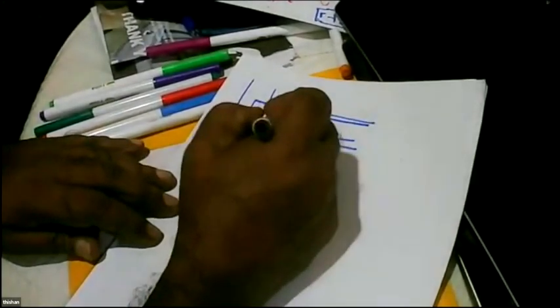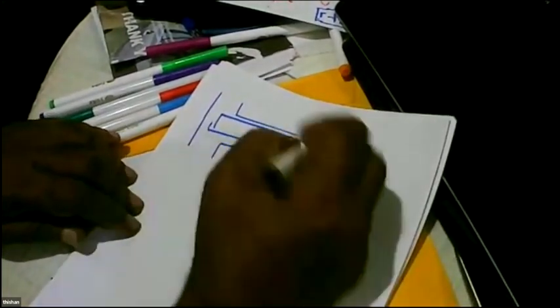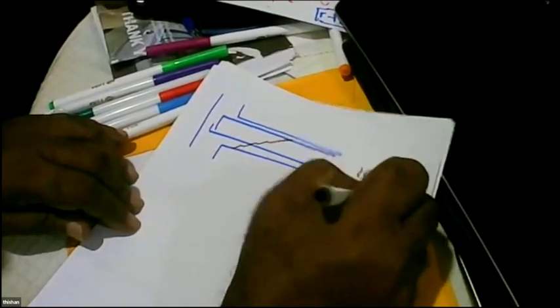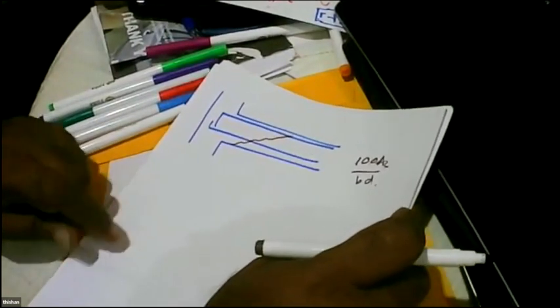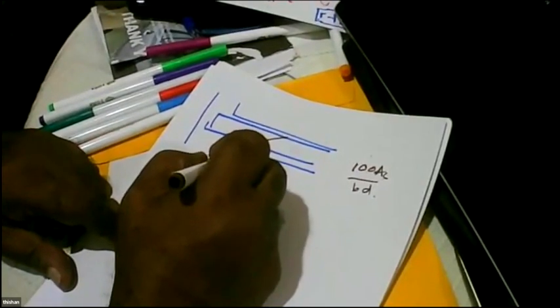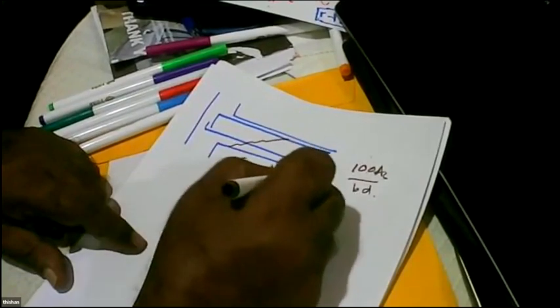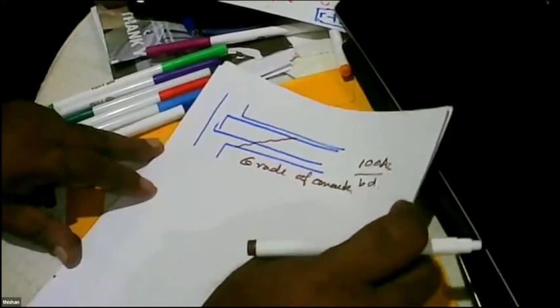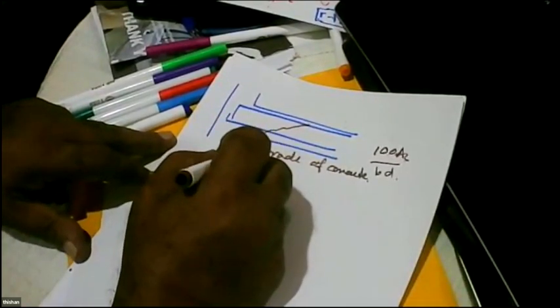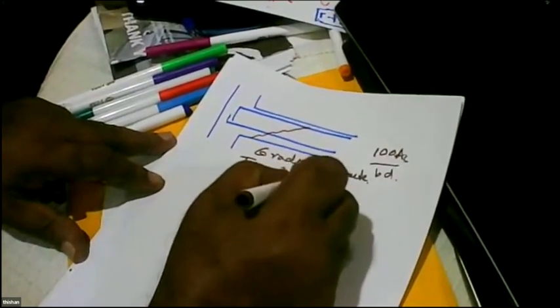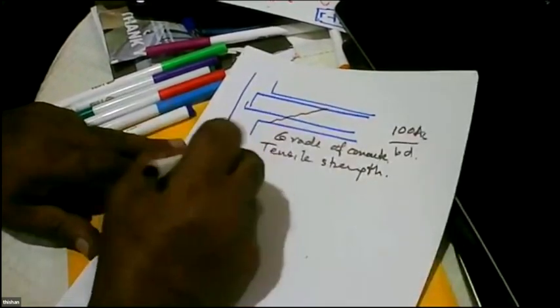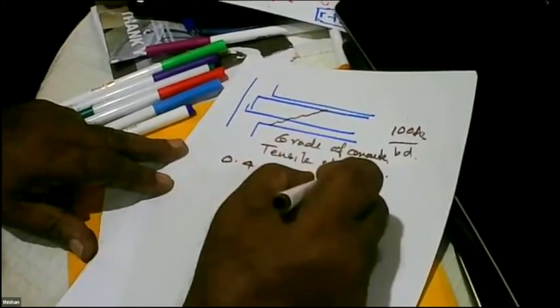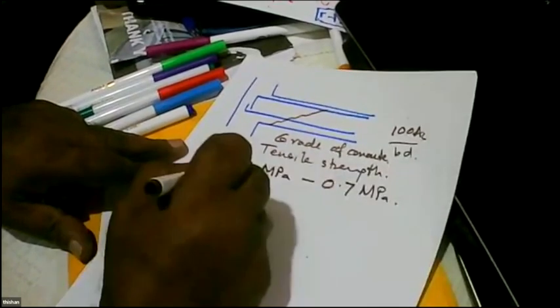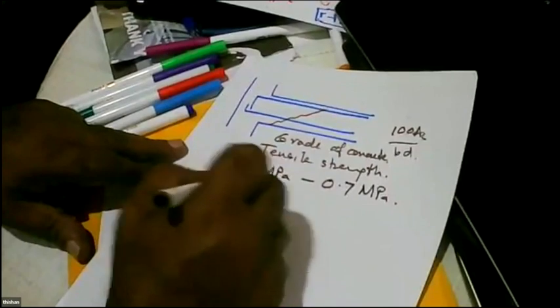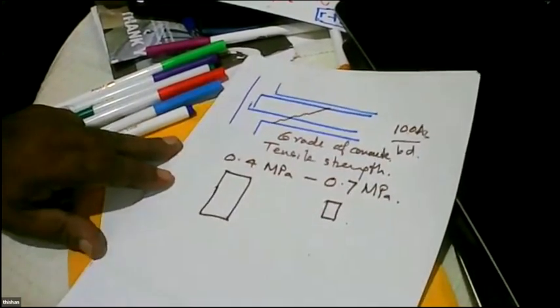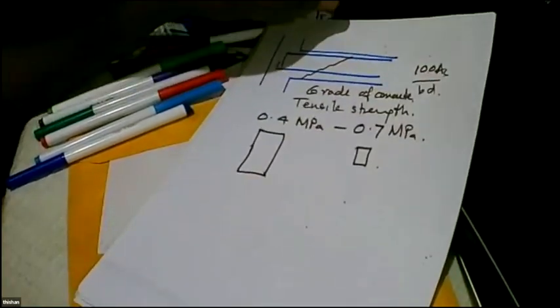So all these capacities will depend on the dowel action provided by these reinforcements. So it's a function of 100 As over bv d. The dowel action: more reinforcement, bigger the shear strength. And then, what else? Grade of concrete, and then the tensile strength. Generally, this value is between 0.4 and 0.7 megapascal. So, big section on this side, small section on this side. Bigger the depth, close to 0.4.